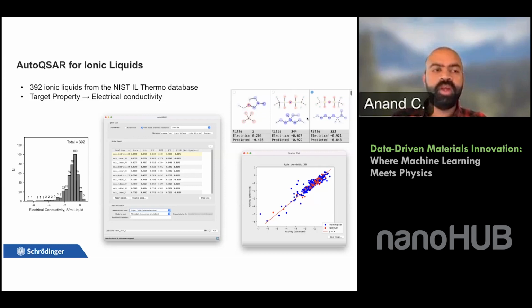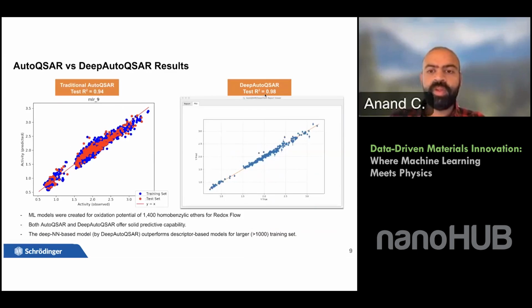The way we benchmark deep AutoQSAR is through fivefold cross-validation metrics. For example, this particular slide, which shows deep AutoQSAR performance, is actually on the holdout set, a test set that deep AutoQSAR has never seen before. We just do a random split, 80%, 20% or 90%, 10%, and the 10% is completely kept apart. Within the 90% training set, we do fivefold cross-validation, and we select the best model based on the fivefold cross-validation. Of course, we also use an ensemble approach where we take not just one model, but the top five models with different architectures and things like that. So the overfitting is reduced by looking at the cross-validation metrics rather than the training metrics itself. We're not looking at the training metrics; we're looking at the cross-validation metrics.